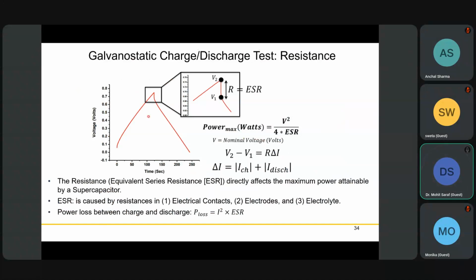One very common observation is this internal potential drop during the charging and discharging curve. This is basically due to the electrical contact within your system, or it may be due to electrode resistance or electrolyte resistance. This equivalent series resistance is a common parameter to calculate how much heat is dissipating from your system, and you can calculate the power loss based on this ESR using this formula. It's a parameter showing how internal resistance affects your system, and how you can improve it by improving electronic conductivity or making good electrical contacts between the electrodes and the cell.